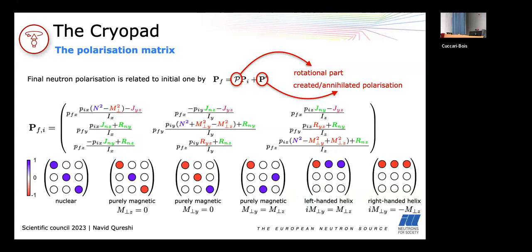And it's nothing to be scared about. I mean there's a lot of stuff in this polarization matrix but you don't have all the cross sections at the same time. For example, a purely nuclear scatterer is the identity matrix. You can clearly distinguish a nuclear scattering process from a purely magnetic diffraction reflection because this is a rotation matrix. You can clearly differentiate the direction of the magnetic moments by just looking at the colors here which go from plus one to minus one. And you can even see if you have a chiral magnetic structure like a helix or a cycloid and you can even say the difference between a left-handed and a right-handed rotation of your spins. This is something you cannot do with unpolarized neutrons. And this ability to extract so much information from one reflection is what makes SNP such a powerful technique and it has contributed a lot to the understanding of magnetic materials in general but especially to magnetoelectrics and multiferroics as I will show in the following.